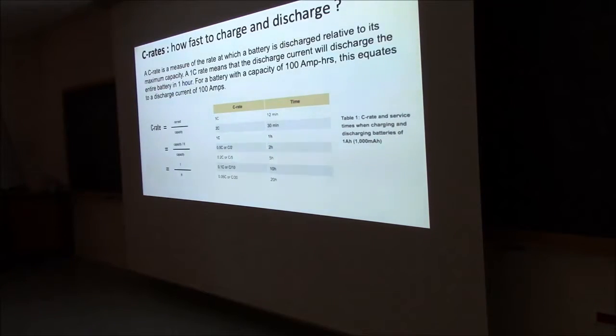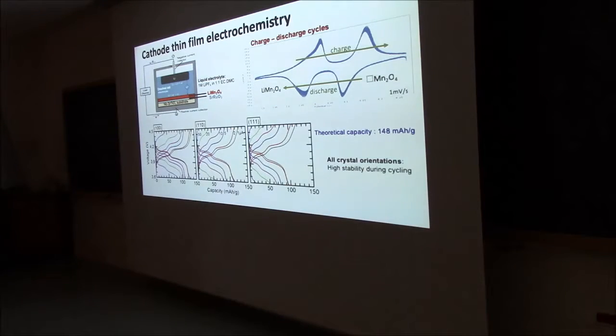Sorry. You fully deplete the lithium in this? Yeah. So like when you do XRD or XPS, you use nothing? Yeah, I didn't put the pictures in, but yeah, we do. We cycle the material, going from 0 to 1, and you do an X-ray diffraction, and you see the different crystal structures. We also have an electrochemical cell where we can do it on the diffractometer. Point is, it's a little bit difficult. These cells are normally designed for bulk materials, and with thin films, we have a substrate, so we have to come from the front.